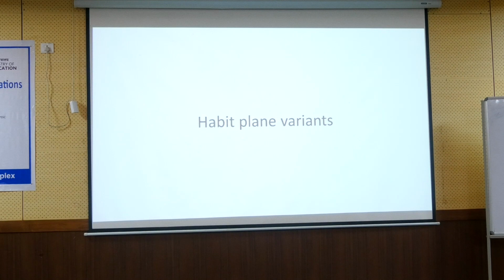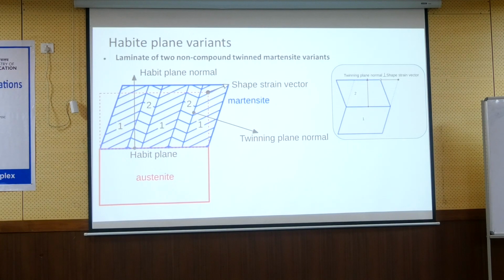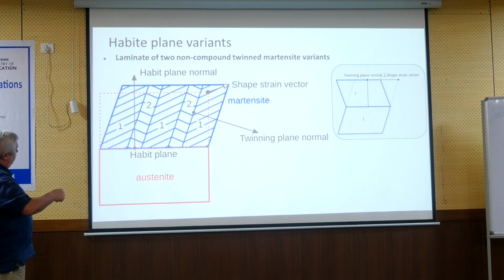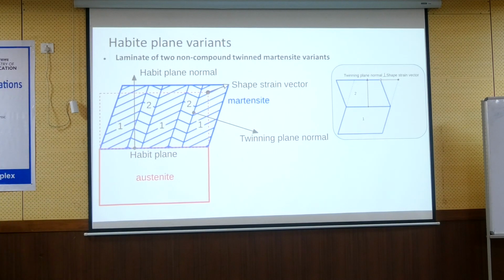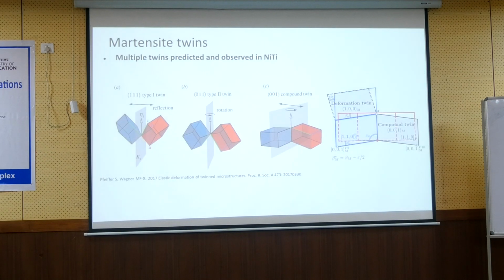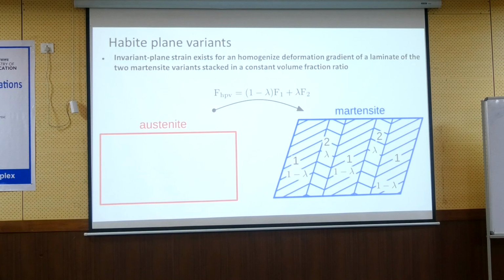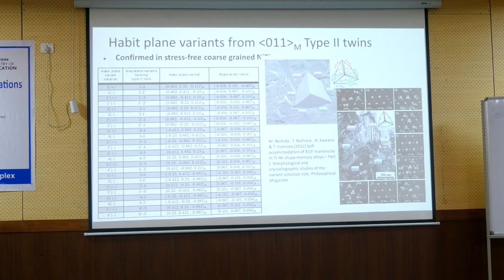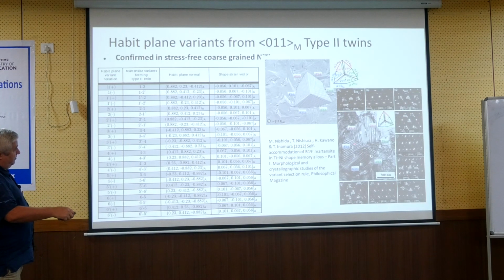So what comes out of this? In the literature, you will find that when the self-accommodated martensite is formed from the austenite, you have such laminates with the habit plane. The PTMC theory predicts that the martensite twins will create the laminates based on the habit plane on the 111 martensite plane, which is here. I don't talk about it much because it is very well covered in the literature: this kind of triangular symmetry with habit plane variants made of type 2 twins on the 011 martensite plane.